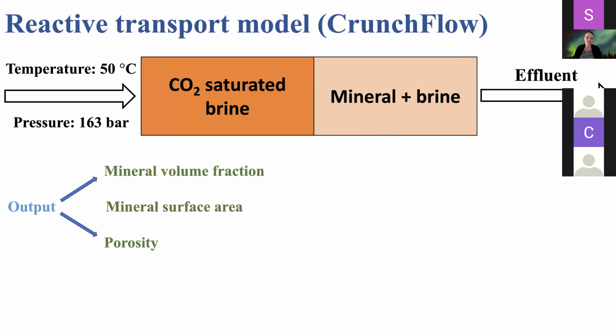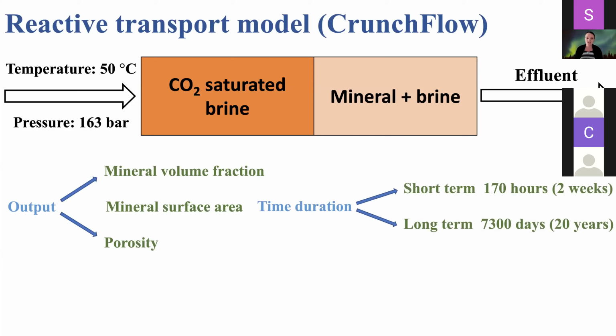We're going to track the evolution of mineral volume fractions, surface area, and porosity. And we're going to look specifically at 2 timescales: a short timescale of about 2 weeks, which reflects maybe what you'd see in the laboratory, and then what would happen at the field site over 20 years.